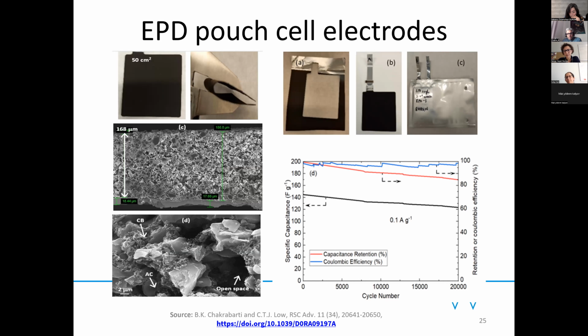Usually we do it with different cycles. For instance, 0.1 amps per gram is quite a low current density. Industries will be using 1 amp per gram, so even higher. And usually for supercapacitors, they will test the lifetime by cycling, charge and discharge, and seeing how many cycles it can do, especially at high current densities. In our research, this is the first time we are showing this, so we are doing it at low current densities. But in future studies, I think we should take into account, as you said, lifetime studies as well as cycle lives. For real life, it will be important. Yes, thank you.